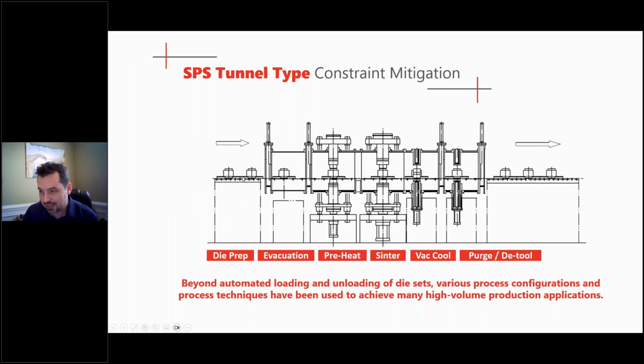Another way of dealing with higher volume demands is a tunnel type system. In this case, the process starts with the material and the die being evacuated under a vacuum, as I mentioned. It then gets preheated to a degree before the plastic range. Then it does the sintering. Then there's a cool down under vacuum so that the graphite doesn't degrade or oxidize. And then it gets purged back to atmosphere. So in the case of a tunnel type system, all of those things are happening simultaneously, and therefore the production rate is tied to whichever single part of that process is the longest, not the sum total of all of those added up together that you would have in a single stage system. So there's several of these units in Japan running for different types of components, and that's another thing that usually is not known to most people in the industry.